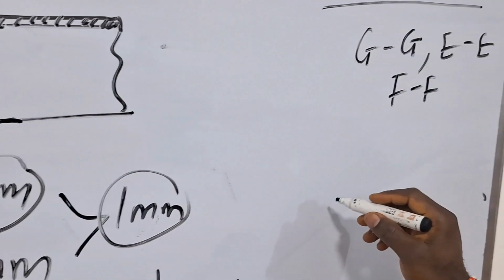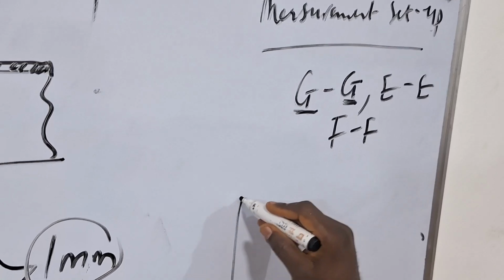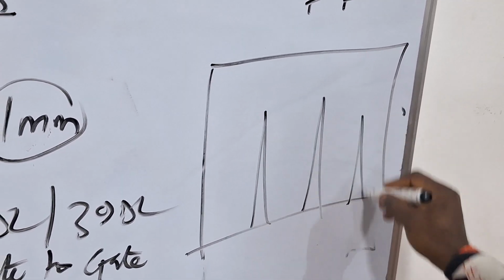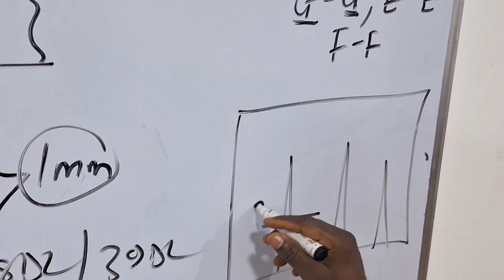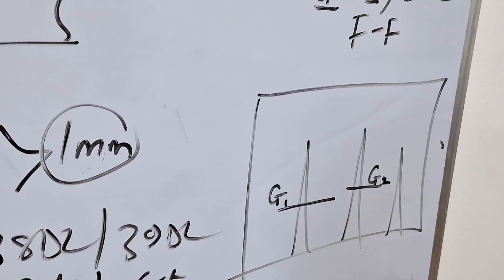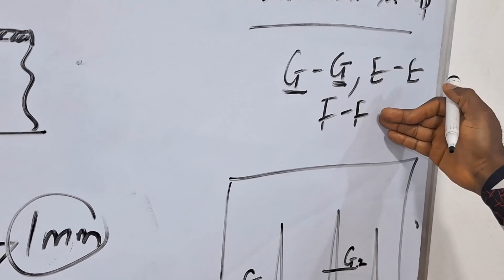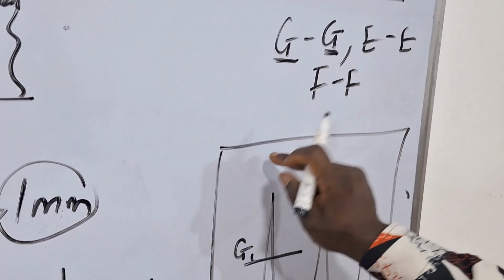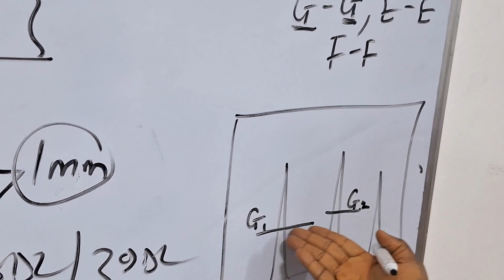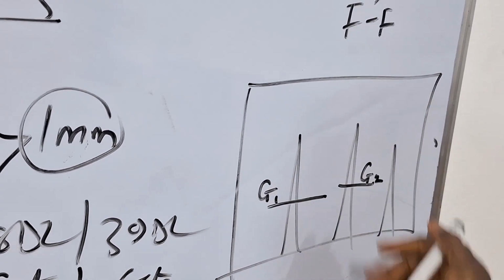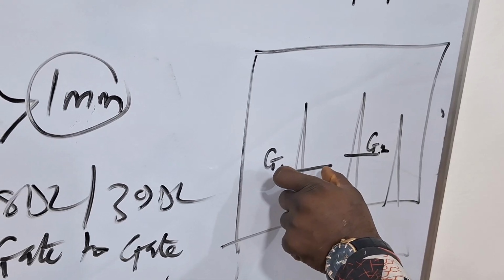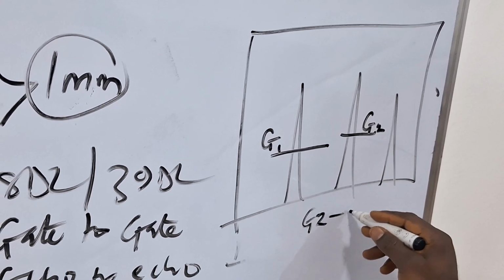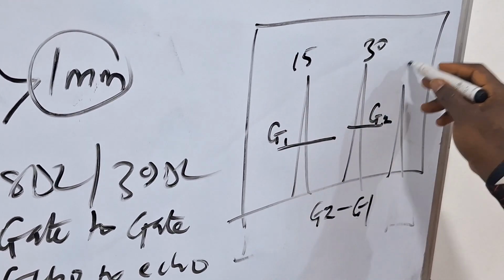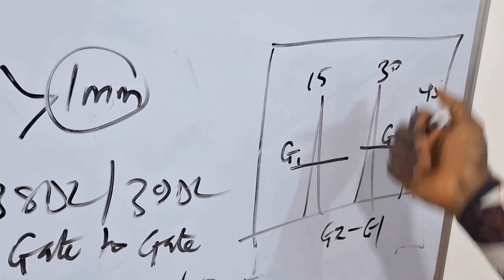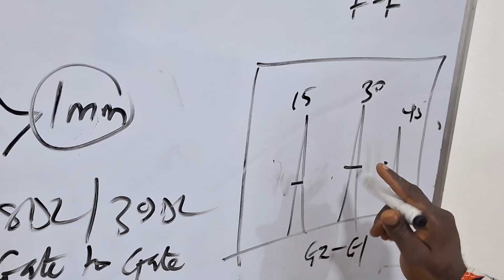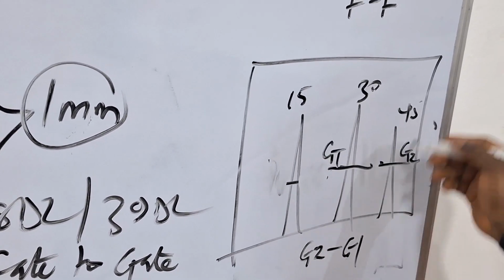In the case of gate-to-gate, the machine recognizes you using two gates. So if I have measurement from the unit where I'm having multiple echo, the machine gives us an opportunity to turn on two gates, my gate 1 and my gate 2. Immediately you set the machine in the gate-to-gate mode, the machine automatically expects you to turn on your gate 1 and your gate 2. So what you manually do, you put your gate 1 on the first echo, and put your second gate on the second echo. Immediately you do this, the machine no longer gives you just the reading of one gate. It gives you a reading of gate 2 minus gate 1. So like we said before, this is 15, this is 30, this is 45. It gives you the reading of 30 minus 15, which is 15. If I decide, on the other hand, to put gate 1 here and put gate 2 here, it does the same thing.